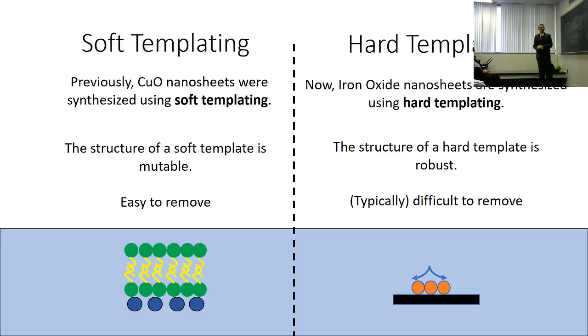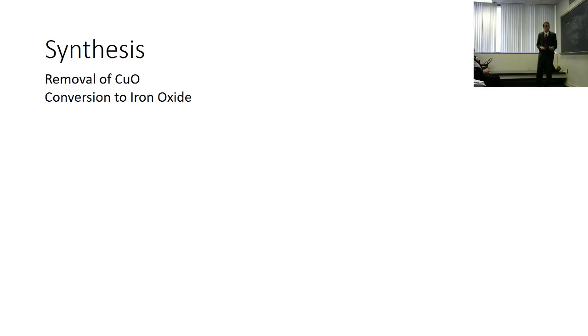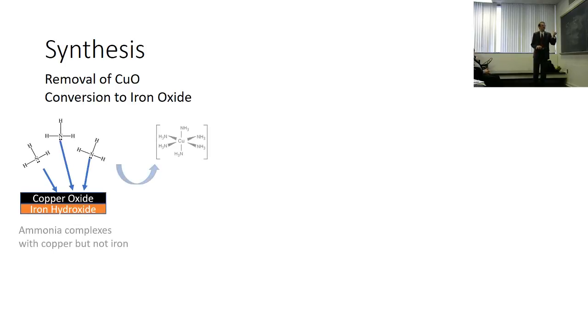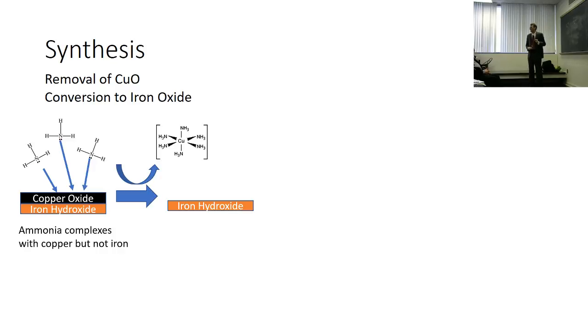But the only downside is it's typically hard to remove these hard templates. So if I want to study these iron nanosheets, iron hydroxide or iron oxide, and get hematite, I have to get rid of the copper oxide somehow. So how do I get rid of copper oxide and not the iron? Well, I just remembered that ammonium hydroxide really loves copper oxide and dissolves it.